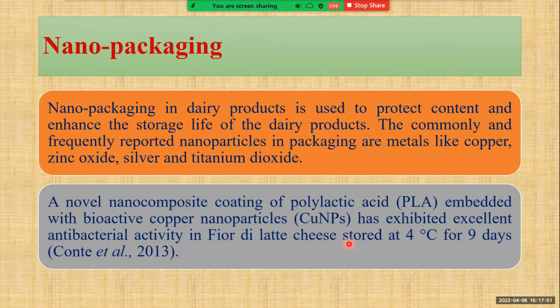Nano packaging. Nano packaging in dairy products is used to protect content and enhance the storage life of dairy products. The commonly and frequently reported nanoparticles in packaging are metals like copper, zinc oxide, silver, and titanium dioxide. A novel nanocomposite coating of polylactic acid (PLA) embedded with bioactive copper nanoparticles has exhibited excellent antibacterial activity in Fior di latte cheese stored at 4 degrees Celsius for 9 days.